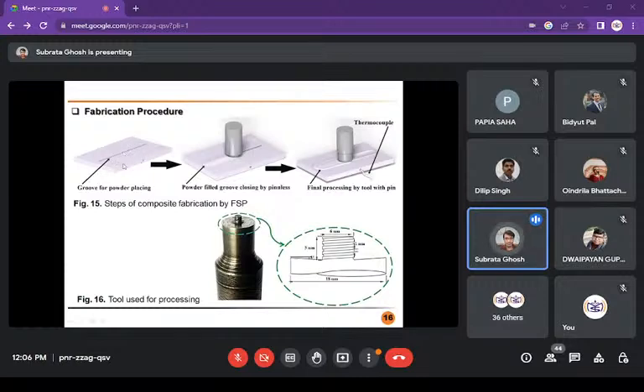After cleaning the surface, we place this workpiece under the tool. Initially, the tool moves with no pin, because the tool should first touch the workpiece. Because of this friction, some skin surface of the material moves, and because of that the groove will be filled, so the ceramic particles do not come out during the main pass. The third step we follow is with the pin. The tool moves with the pin at some particular speed. At that time, the ceramic particles inside the groove are distributed over the workpiece material. That is the main idea.